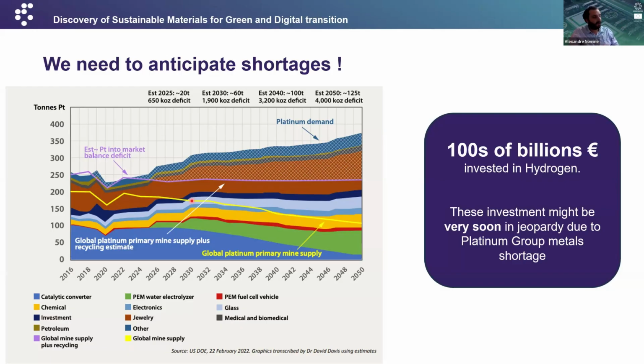This doesn't happen. So the decrease in the mining, the primary production of platinum, will also reduce the production of iridium, rhodium, osmium, palladium, and all the byproducts. And that might be a big issue. So we should also take it into account. We should very much recycle iridium, even more than platinum, actually, because there are mines of platinum, there are no mines of iridium. Iridium is just extracted out of platinum, just to keep that in mind.